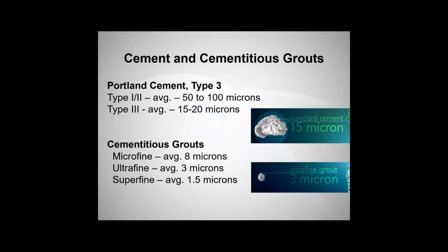Jumping into cement and cementitious grouts, obviously I just talked about the Portland cements. We have type 1 and type 2, average micron sizes anywhere from 50 to 100 microns, whereas the type 3 Portland cements are 15 to 20 microns. Then, further refining those micron sizes and dropping down to the single digits, we get into the microfine cements, which have an average of 8 microns, the ultrafine cements of 3, and superfines of 1.5. To put that in perspective, a human hair is about 70 microns, to give you an idea of relative scale.